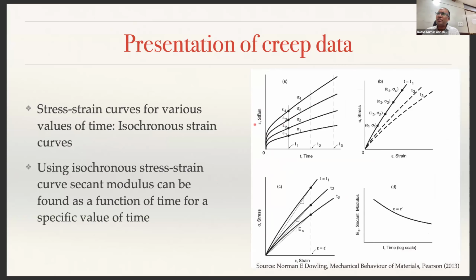So for the creep data, you can plot stress versus strain versus time for different sigma 1, sigma 2, sigma 3, and the same data can be represented in different ways. That's all, right? So stress strain curves for various values of time, stress and strain at different time points, are called isochronous stress strain curves. And using these isochronous stress strain curves, we can measure the secant modulus, what is called the slope at a given strain. For a given strain, you can draw a straight line, and then the slope of that line is what we call ES, and that can be plotted as a function of time, right? At a given time, the value of ES for different times will be given, and then you can plot the ES for that particular thing, and so on.